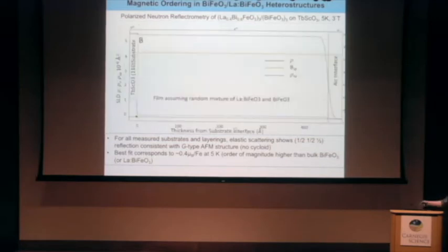So something's going on here where we have what looks like a uniform, or some non-trivial, magnetization in our film that's about an order of magnitude higher than what's expected for bismuth ferrite. Our fit, when we convert the scattering density, corresponds to almost a half μB per iron site. And that's assuming a uniform magnetization. So if it's only in the bismuth ferrite, only in the lanthanum, or only at the interfaces, it's actually a higher magnetization.